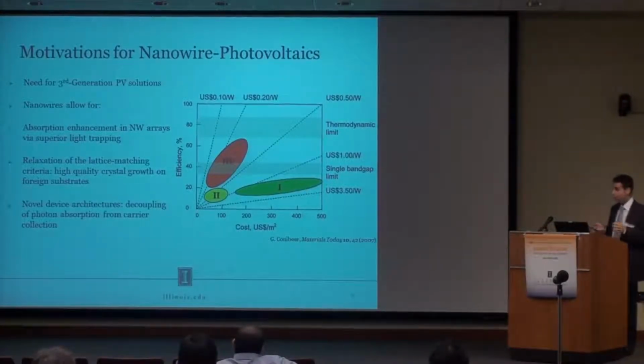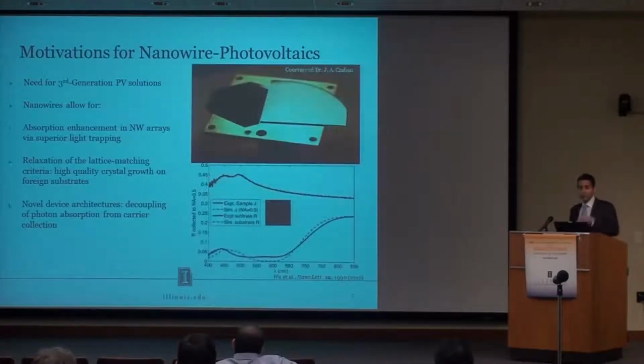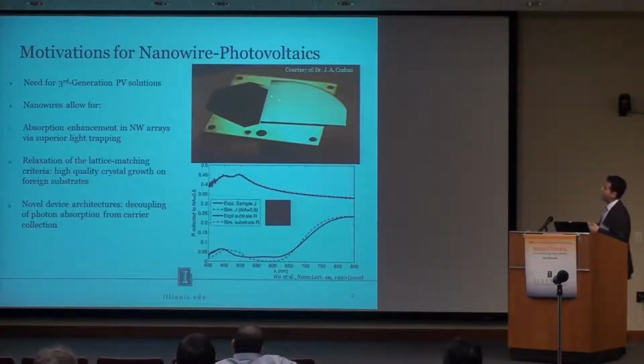So then the question is still, why nanowires? There's three main reasons why we want to use nanowires for solar cells. First off, they allow for absorption enhancement. If you take a look at this photograph here, I'm showing you a bare gallium arsenide substrate. It's perfectly reflective. You can see yourself and it acts as a mirror. Now, if we take the same substrate and grow a nanowire array on it, you can see that it's almost allowing for unity absorbance. Now, this is based on two principles.